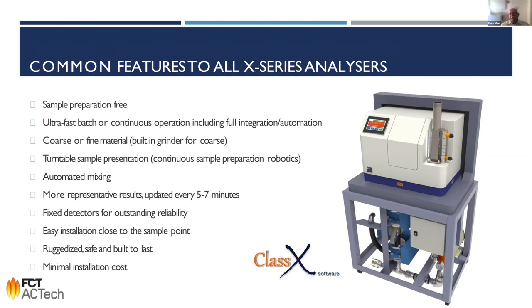You might need about 15 to 20 minutes per week for a little bit of cleaning and looking after the system, but it is not like the very complex installations of a robotic laboratory or other equipment where you really need to have a champion next to it. It really runs fully unattended. And you get a result every 5 to 10 minutes, I would say, which can be directly fed into your process control software or your LIMS system, etc.